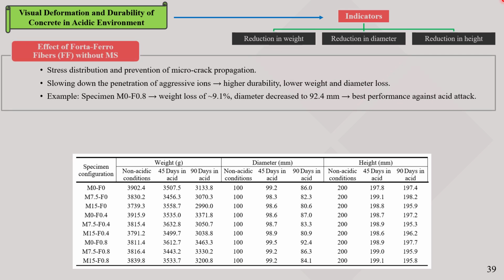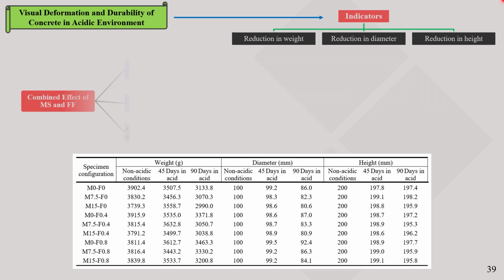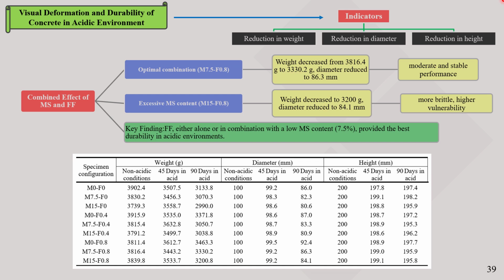Under acidic conditions, the higher the microsilica content, the greater the loss of weight and diameter. In contrast, increasing the fiber content reduces weight and diameter loss, as the fibers help distribute stress and prevent the propagation of microcracks. When microsilica and Forta-Ferro fibers are used in combination, the performance is moderate and relatively stable, provided that excessive microsilica is not used. Overuse of microsilica can lead to brittleness and make the concrete sample more vulnerable to damage.